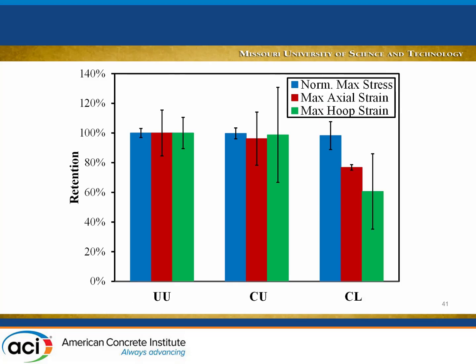So here's a sample of the results for the first group, which was not placed in water, just inside the environmental chamber. The retention here is 100%, which means you don't lose anything after the exposure. For example, the hoop strain was very sensitive. We have a very high variation here, but generally you lose about 40% of your strain. This is crucial, because it would affect your confinement and ductility if you design for seismic. Strength-wise, we didn't really lose much, and again, this is related to the fact that you embrittle the fiber, so you didn't see much strength reduction, but you see axial and hoop strain reductions.